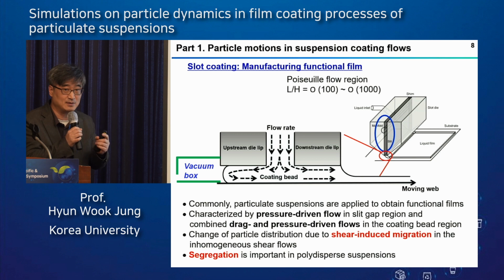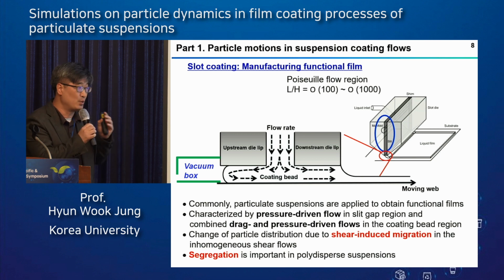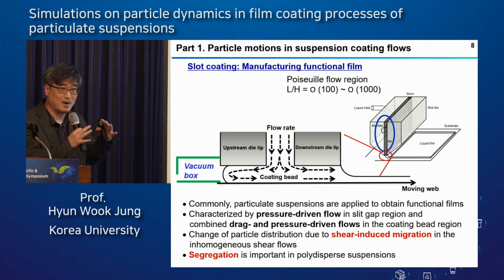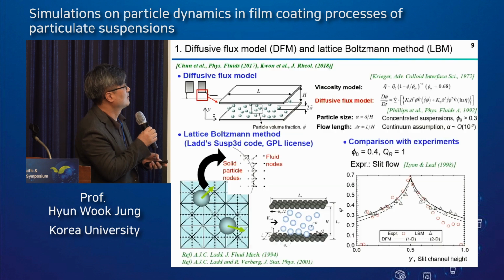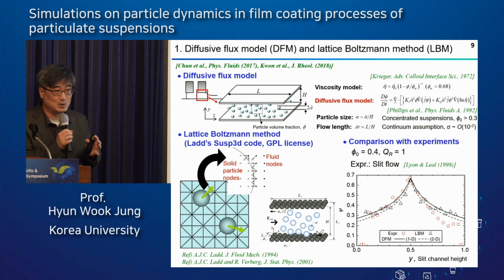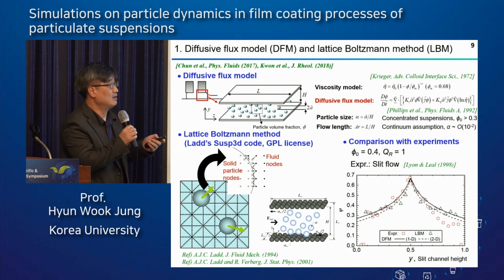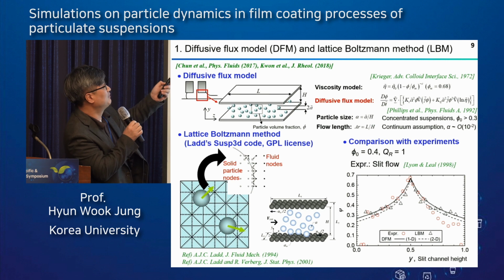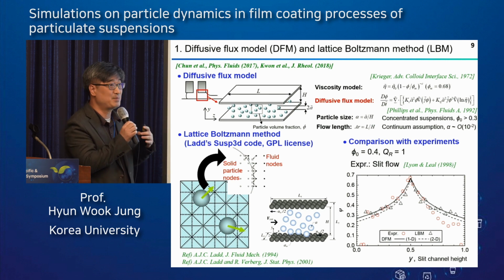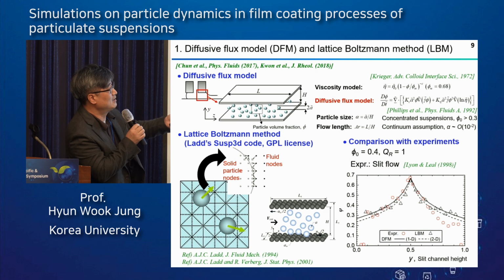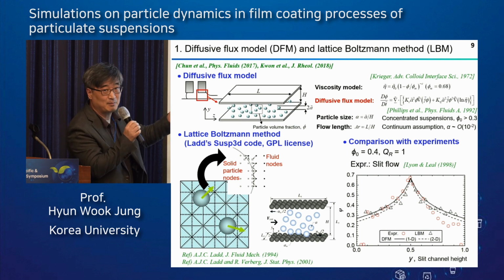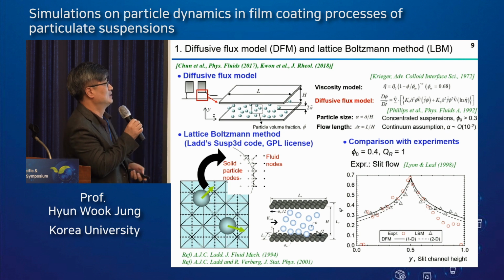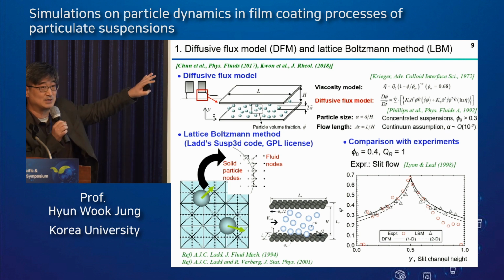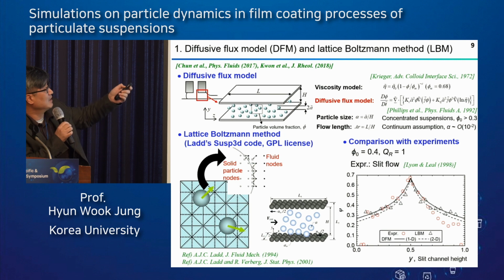Also, if we consider polydisperse particulate suspensions, we can see some segregation behavior between the large and small particles. To numerically solve particle motion in the flow field, we applied a continuum-based diffusive flux model, a phenomenological model developed by Professor Phillips, and a mesoscale particle-based lattice-Boltzmann method. More detailed methods will be explained in this talk.